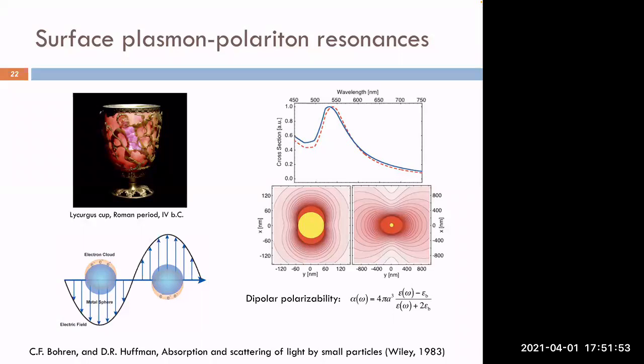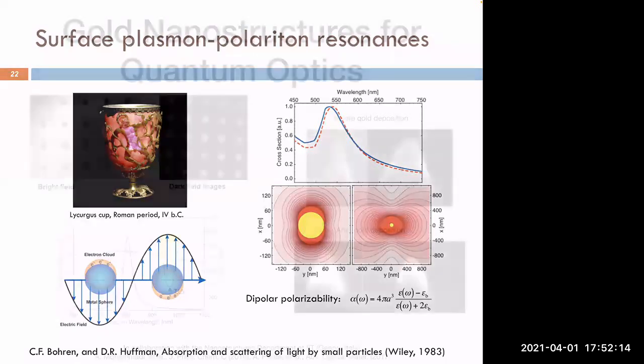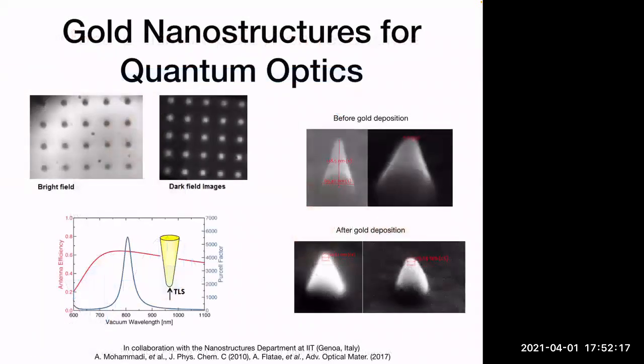if you are able to place them in the near field, because the strong near field creates a kind of very strong density of photons. And as you know, in the spontaneous emission process, having a large density of photonic states improves the emission rate. So of course, we need to do it in a certain way, not just with a nanoparticle. And so here we created nanostructures based on gold, in which we use the shape of a cone, because you can get a very sharp tip and at the same time tune the resonance of the plasmon.